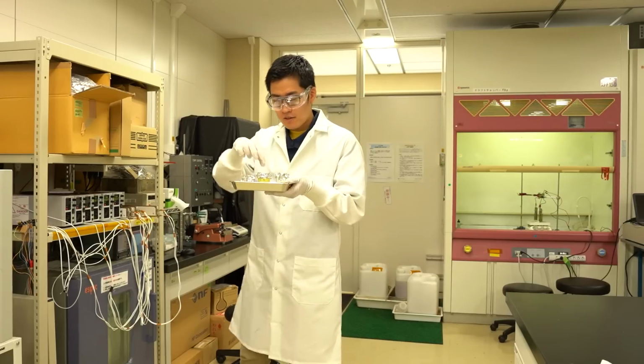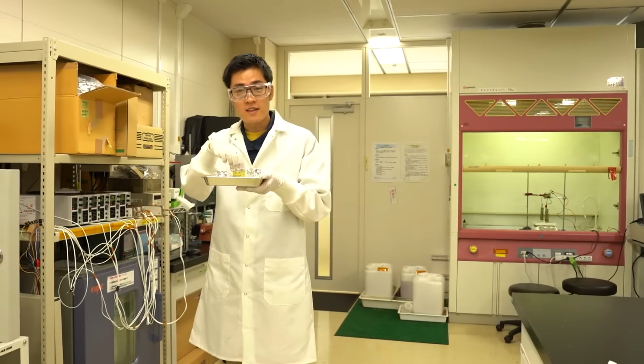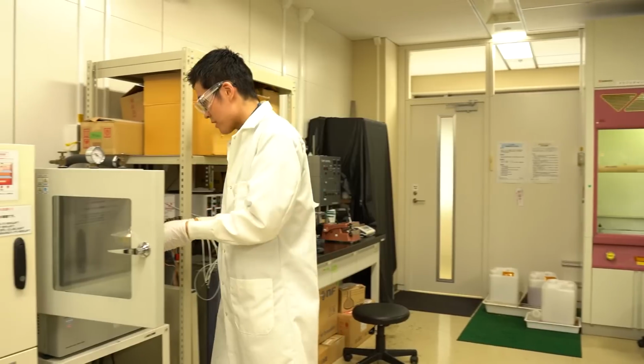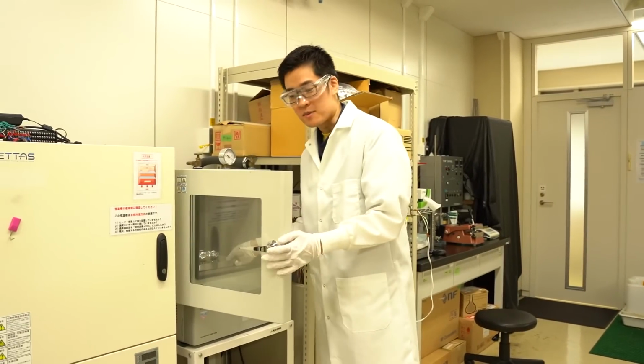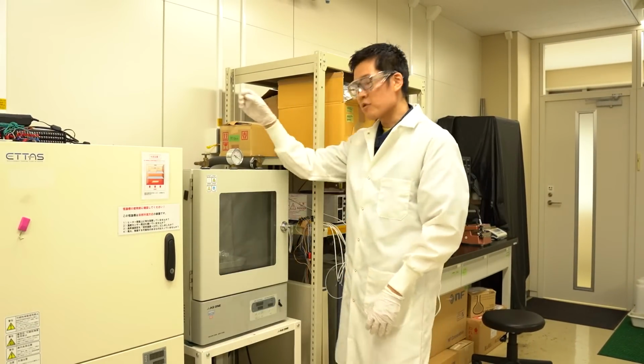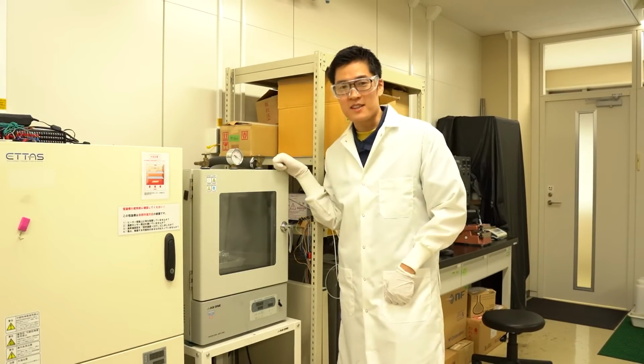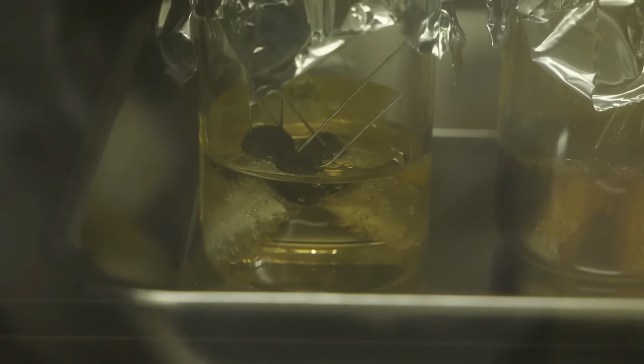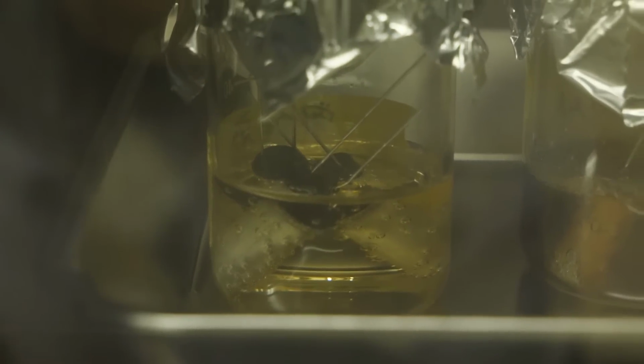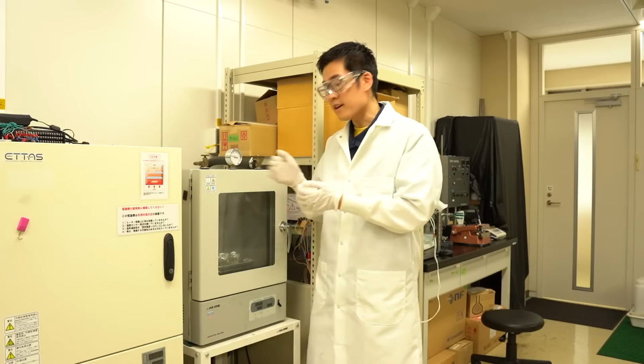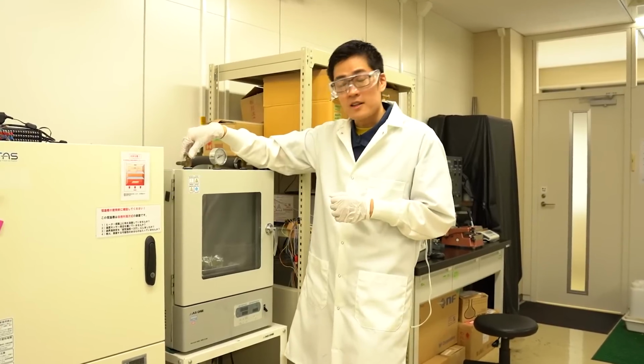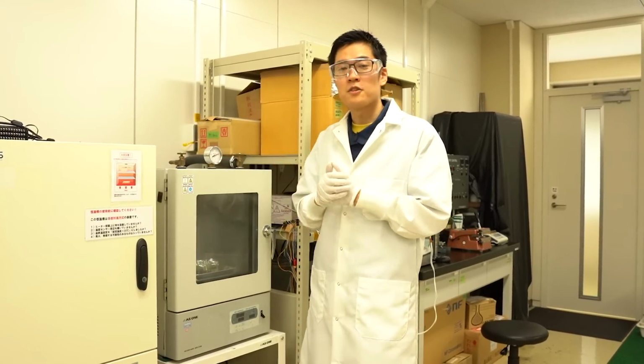Let's start. I'll put these electrolytic capacitor elements immersed in the electrolytes into this machine. The machine lowers the pressure. Put in and turn on the switch. The impregnation has started. I'll leave the elements for a few minutes under low pressure inside the machine. Then the electrolyte will permeate into the surface of the electrolytic papers and anode foils. I waited for about 10 minutes. It seems the impregnation is finished.